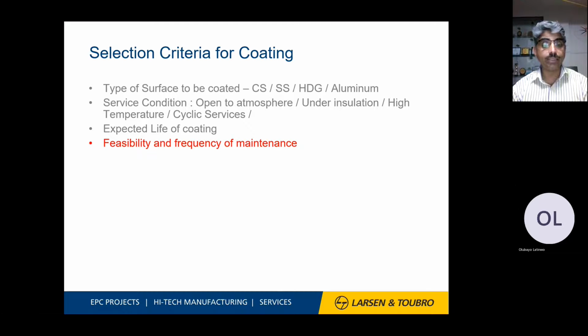Nowadays there is a standard which says more than 25 years of coating life. It is normally called TSA, that is thermal spray coating. That is the metal coating or metallizing, which has more merits in the present scenario for offshore platform rigs. Then feasibility and frequency of maintenance is also a criterion for coating selection. If the frequency is lower in number, or you can say the cycle time is higher, say 5 years, you do one particular coating DFT, dry film thickness, which gives more life. If it is lesser, if it is 1 year or 2 years, you have to change your coating system and you can refurbish the coating based on the life of that particular maintenance. So your asset integrity teams are the team which decides these maintenance cycles.